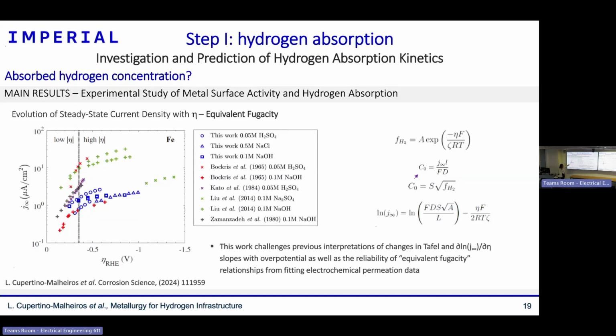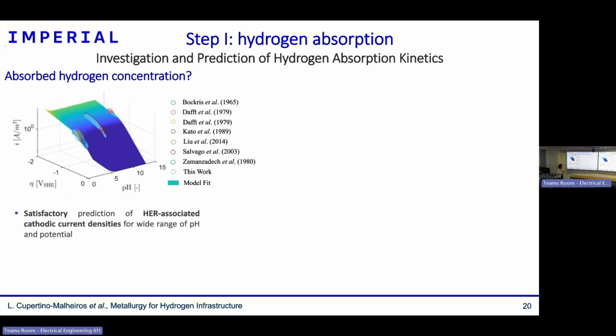And what this work has shown, when I plotted the data of my work and from previous works, is that there are some limitations on getting equivalent fugacity from this approach. There is quite a lot of dispersion, so it's difficult to establish this relationship.